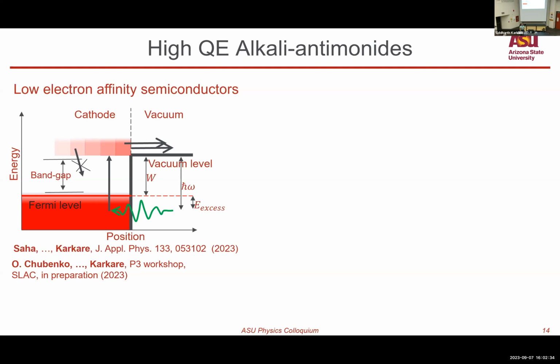So the electron-electron scattering process, which is a major energy loss process for electrons in metals, which really causes their quantum efficiency to be very small, is inhibited. And most electrons that go into the conduction band, if they reach the surface, they get emitted, and they keep lingering around in the conduction band for a long time. And that gives us a very high quantum efficiency from these materials. Now, alkali antimonides is a subclass of these materials, which has a high quantum efficiency as high as 10% in visible light.